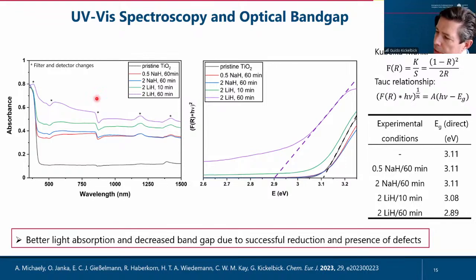Of course, you have seen that we generated black titanium. And if we generate black titanium, you should see that in the absorption spectra. The absorption spectra also help you in detecting the band gap. You can do an analysis called Kubelka-Munk analysis. You look at a specific absorption band, and then you take a linear regression of your signal, and then you can tell something about the band gap in your material. And what you see is that you have a band gap shift to a lower energy, and this is due to the reduction of the titanium to the black titanium. Okay.